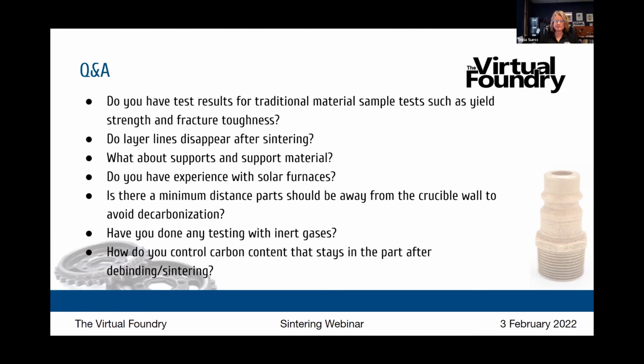So what about supports and support material? If you have a dual extrusion 3D printer, you can use a separate support material, and that can be anything that you would use of standard PLA, including regular old PLA. Yeah. And PVA, that water soluble support material. If you have a single extrusion 3D printer, you're going to use more filament as your support material. All of those supports that are printed with your part are broken off, or they're removed, or you put your part into the crucible for firing.